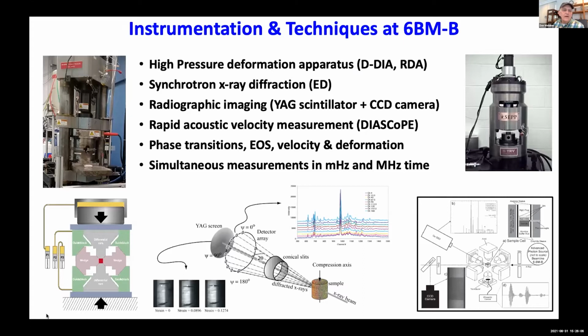Okay, so moving to APS, just a brief reconstruction. On the upper left, you see a picture of the D-DIA, a cartoon of the D-DIA on the lower left. This is the pressure generating system. The upper and lower rams have separate hydraulic systems to allow the differential stress to be added. We take images of the sample. This allows us to measure strain and so forth of the entire sample during the experiment.